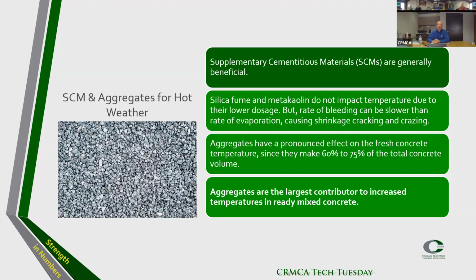Aggregates, if they're hot, they have a really big effect on the fresh concrete temperature, since they make up about 70-75% of total concrete volume. So aggregates are by far the largest contributor to increased temperatures in the ready mix. That's something we need to consider.